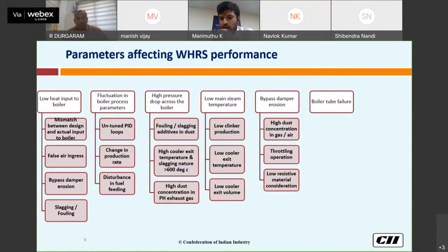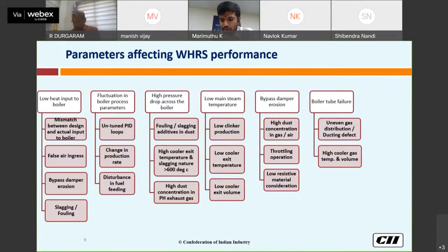Then another one is boiler tube failure. Boiler tube failure mainly occurs due to uneven gas distribution and ducting defects. If the gas distribution is not good, at some areas we will get more gas, which will cause more velocity, so definitely the erosion will take place. So this is one reason we observe.